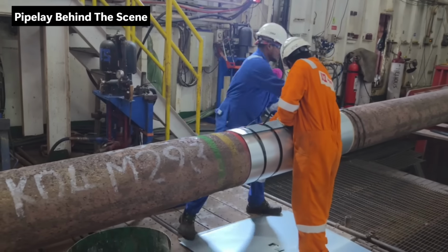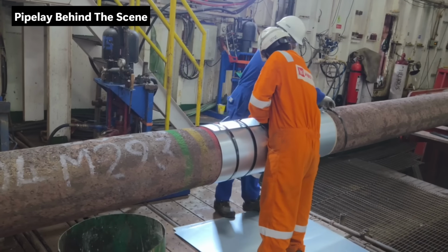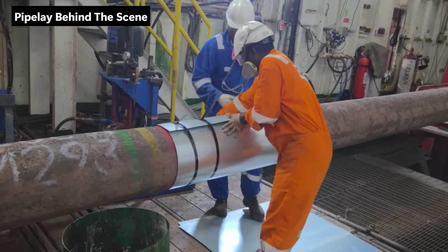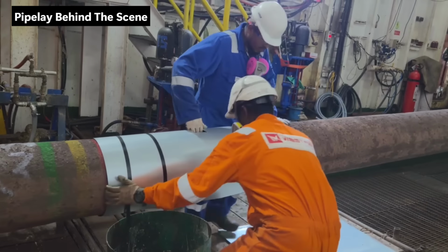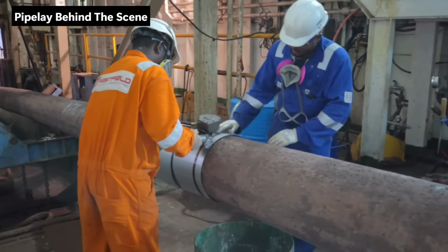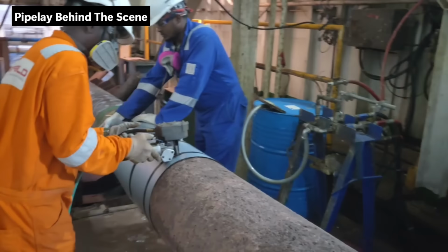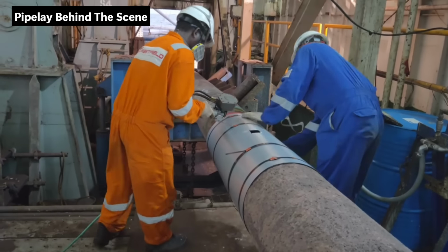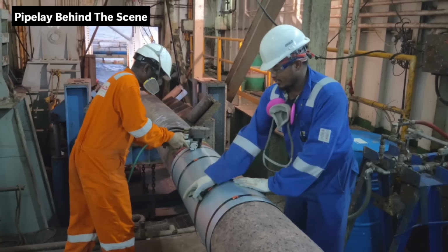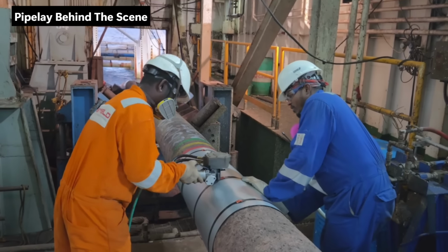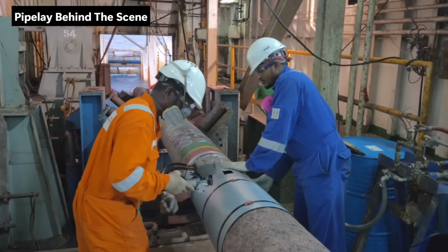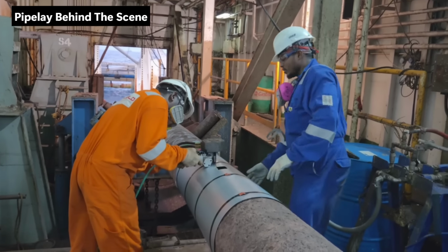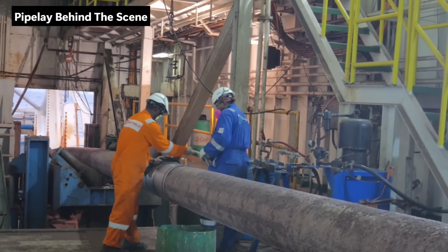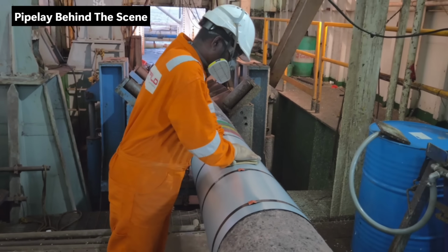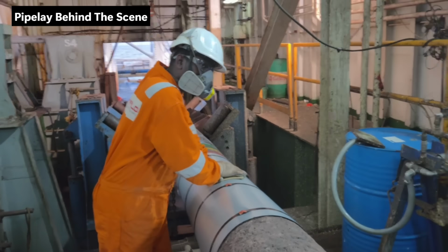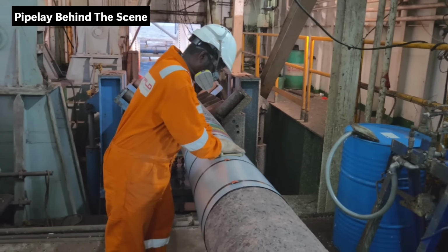Foam coating is applied at the field joint. What you are watching here is that process. A sheet of foam material is wrapped around the pipe at the joint and secured in position. Then, through a small hole, a foam compound is injected into the space between the wrap and the pipe. The compound expands, fills the space completely and sets hard. This makes sure that the seawater never penetrates down to the raw iron pipeline.